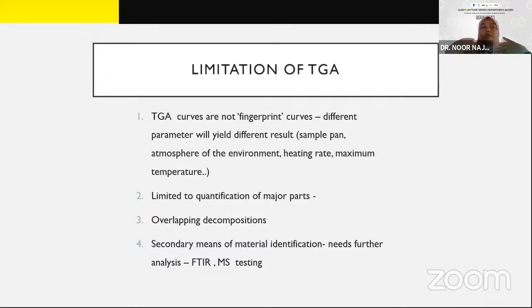So that's why before you send your sample for TGA or DSC analysis, you need to read the journal and get the range of temperature used for that sample, and what kind of environment gas they use, in order to make sure that the result you get is accurate and related to your sample. And this TGA is also limited to quantification of major parts, and sometimes you will get overlapping decomposition results. Okay, and that's why you need to do further identification by using FTIR or mass spectroscopy testing.